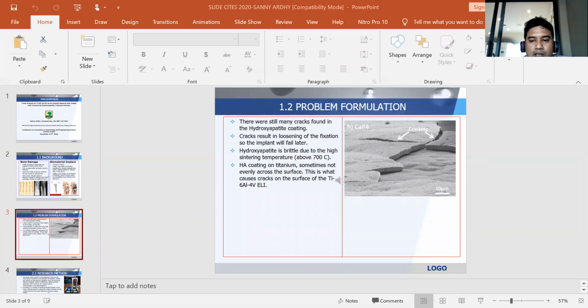Problem formulations. There are still many cracks found in the hydroxyapatite coating. Cracks result in loosening of the fixation, so the implant will fail later. Hydroxyapatite is brittle due to the high sintering temperature above 700 degrees Celsius.